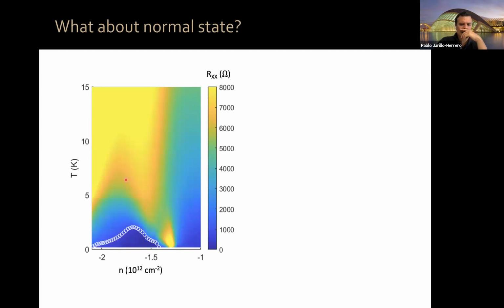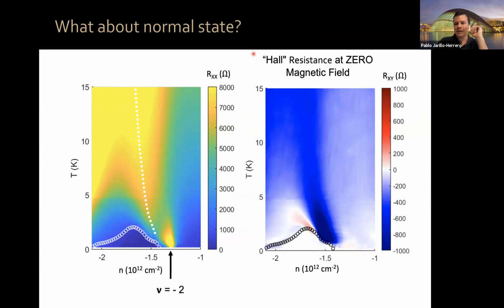So this is the resistivity versus temperature and density for the device. This is the banana. This is the correlated insulator state at low temperatures. So that's filling factor -2. Here we have our banana with a depletion of TC. Now, this is a measurement of RXX, okay? Now, let's see what happens if we do a measurement of the transverse voltage, okay? The equivalent of the Hall resistance, but at zero magnetic field, yeah? In principle, we would expect that measurement to give you 0. However, as you can see, there is a region of very strong RXY behavior, okay.